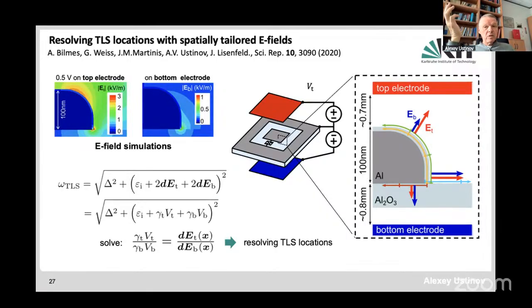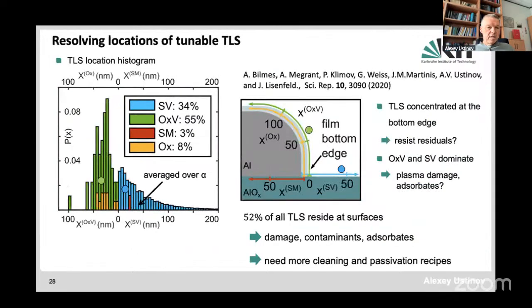Of course, electric field is always perpendicular to the surface of a superconductor. This actually helps to just neglect the tangential component and then have one-to-one mapping between the field induced by the top and the field induced by the bottom electrode. And then by measuring the respective reaction of the defects to these two different fields, we are able to count the number of defects at different surfaces and actually as a function of distance from the surfaces. And the result of this tedious analysis is shown here.